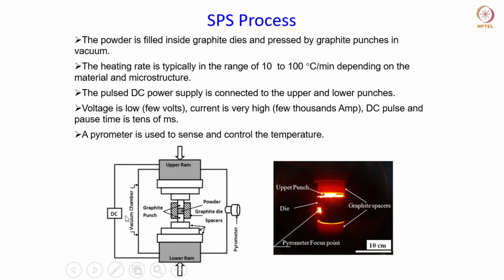So here is the schematic of the basic setup that is used for SPS. As I said, you have graphite die and punch sets which are used to pressurize the powder and also to carry the electrical current to the powder. And then you have this upper and lower ram through which the powder is pressurized, and these upper and lower rams are connected to the DC supply. And here you have the pyrometer to monitor the temperature.